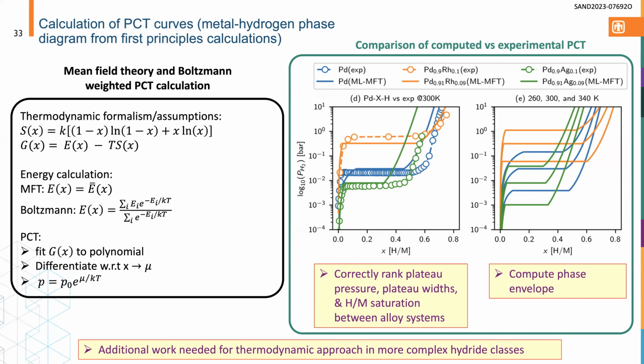So the critical things that we see are that we're able to correctly rank the plateau pressure, again, spanning many orders of magnitude in the palladium hydride system. That happens when you notice how small of a fraction you're actually doping of rhodium and silver, for example, and that produces many orders of magnitude increase in the plateau pressure. What's also really interesting is that the model correctly gets the saturation capacity ranking correct, and this goes against what I just said, right? In this system, the less stable the hydride, so the higher the equilibrium plateau pressure, the higher the capacity.